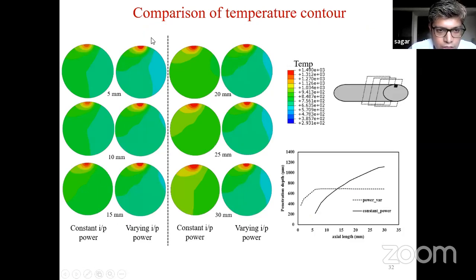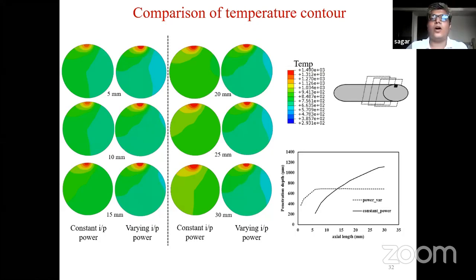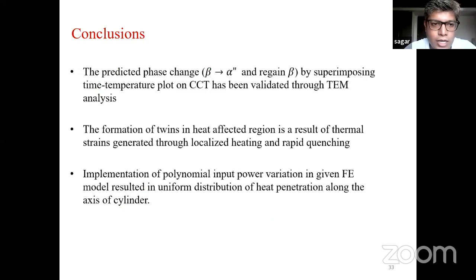If you look at these sections, for every cut, and those cuts were made at 5 millimeter, 10 millimeter, 15, 20. At every interval of 5 mm we have different cuts, and from those cross sections we could see how much the laser depth penetration is affected. So with this model we could get a proper, constant depth of penetration. And with laser treatment we have already seen how the machinability can be increased with reduction in cutting forces. So combined, these two make up this model.